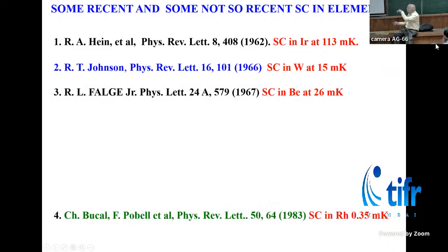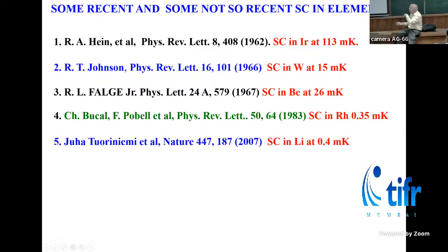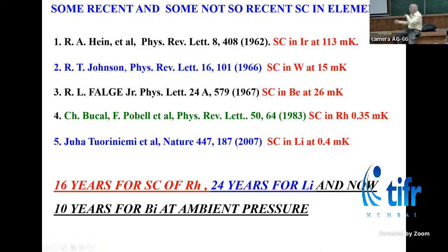And this is the sequence of how the elements started showing superconductivity. So the latest one is, not so latest, the rhodium superconductivity was about 350 microkelvin. That was from my mentor, Frank Pobell. Then his competitor in Helsinki showed the superconductivity in lithium. This is a very, very tough experiment, because lithium, you just take it out and within a few seconds, it just becomes a powder.